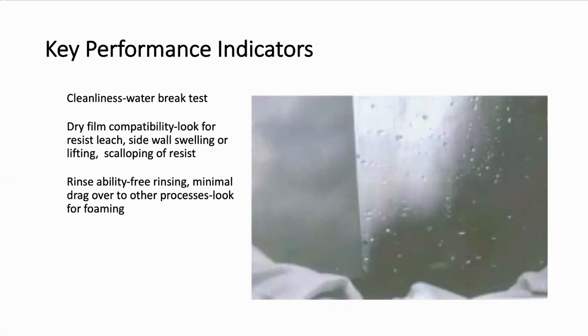If you get this type of situation, where after you think you've cleaned the board you dip it in water and it immediately beads up, that means the surface is not clean. There's something still on it. What you really want to do is see this. You want the laminate, if it is clean, to be able to hold a sheet of water for 15 to 20 seconds before it breaks. It may be somewhat simple, and again, it's a qualitative test, not a quantitative test, but at least it gives you some understanding, and it'll help you get over the hump of, is my surface clean or not?